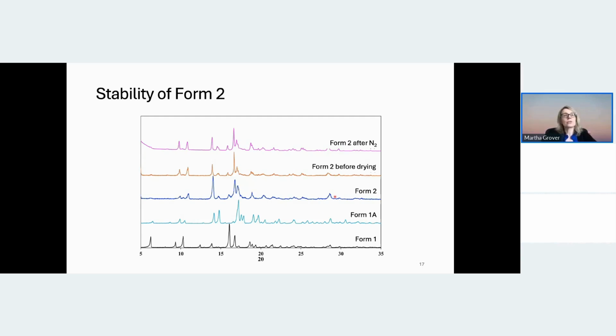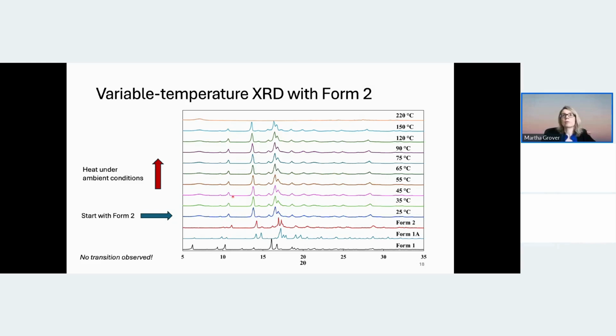But finally, we wanted to understand the stability of Form 2. Recall that was the original motivation, to produce a form that was physically stable. And so we can see here, if we compare the Form 2 that we had previously characterized before drying and then after drying in nitrogen, that we have very, very similar characteristics in the XRD. They appear to us to be the same before and after drying, and also in the variable temperature XRD.